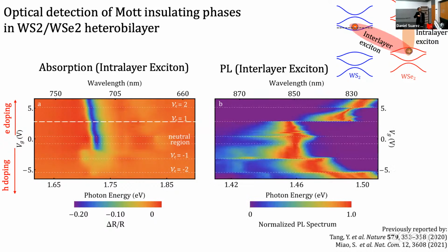Another way to do it is by using the interlayer exciton, which is an exciton formed when an electron in the tungsten disulfide binds with a hole in the tungsten diselenide. So it is indirect in the sense that each particle is in one of the monolayers. And in this case, the Mott insulating state reflects as a gap in energy in the photoluminescence emission of the material. So these two possibilities were demonstrated, and we are going to use in particular the second one, the photoluminescence spectrum, and our interest relies on the electronic doping of the material.